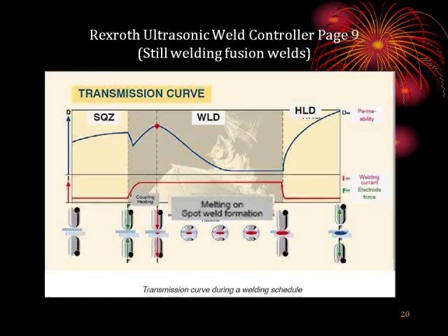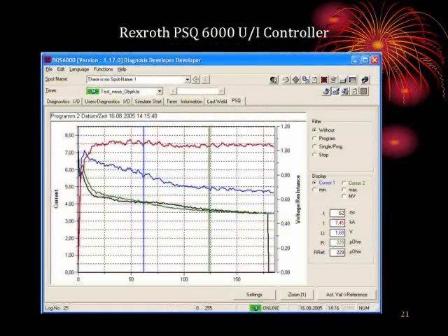This is the transmission curve versus the time. And if you notice, at the very short time right after the weld started, they claim it started melting, and melting, and again melting, until this whole thing is stopped. The weld is terminated. In real life, melting only happens at 1500 degrees C for steel. And as soon as you melt any amount of metal, the expulsion happens. And simply, this idea that you can keep on melting from the very beginning until the end is incorrect.